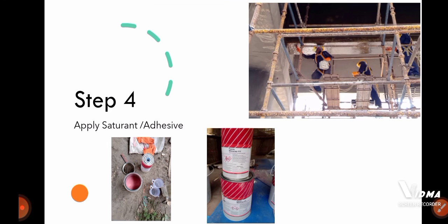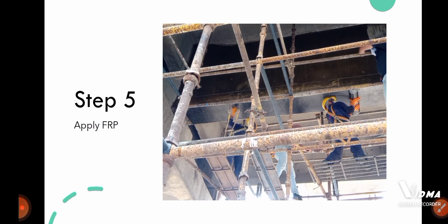Primer is applied, now I will apply the saturant or the adhesive. Here you can see I am applying Fosroc saturant. This guy is applying the adhesive or the saturant over the primer and the color is something like this, very beautiful pink color. The name of the chemical here from Fosroc is Nitowrap 410. There is a hardener and a base - there are two components of the saturant. After mixing this saturant you are applying here, and within the application of the saturant or adhesive, maximum 30 minutes is allowed. Within this 30 minutes you have to apply your FRP.